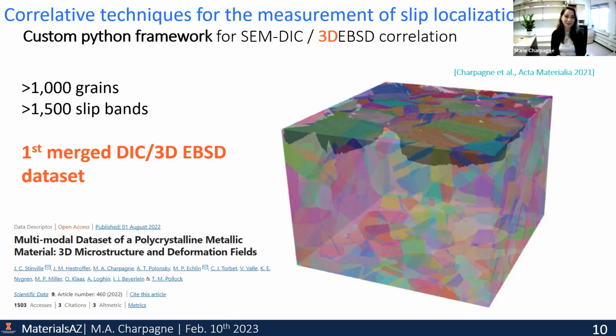And it was very convenient in Teresa's group. We have this tri-beam microscope that's now commercialized, but we can really collect very large volumes of 3D materials. So we came up with this very first merged DIC 3D EBSD dataset, which is very, very insightful. It has over 1,000 grains and over 1,500 individual slip bands that are featurized and flagged thanks to image segmentation and machine learning codes. We believe that this dataset is going to be useful to the community. So for this reason, we made it available this year in a dedicated article. And you can actually download this dataset and model it or study it from a theoretical standpoint, if you like.